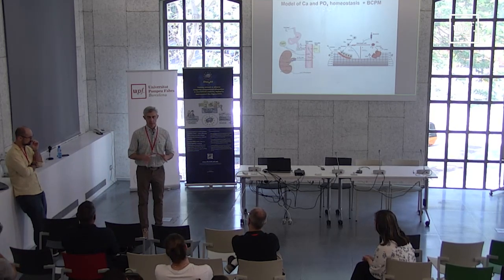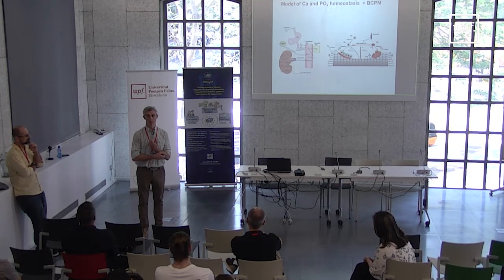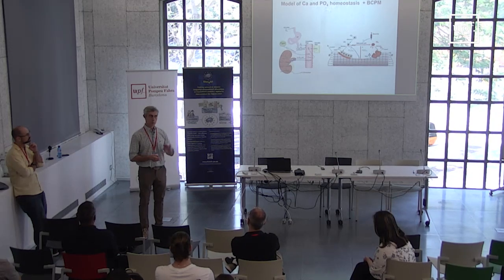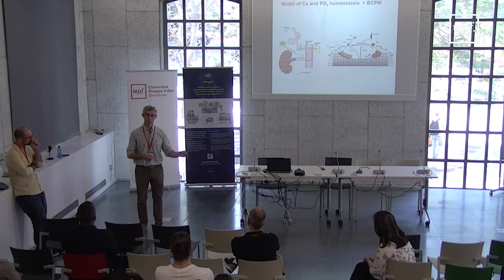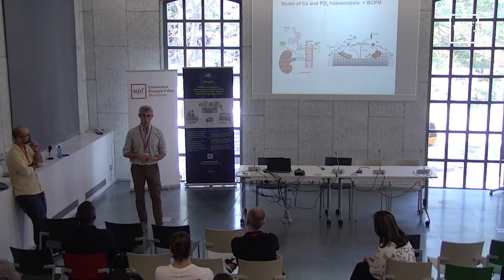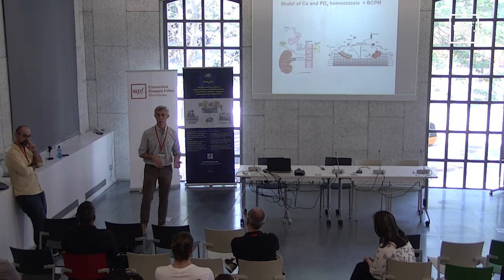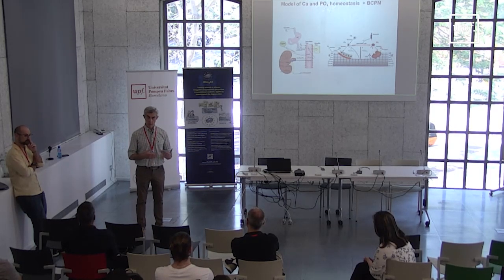Yep. This model I presented today is just a local model. So we could say that it's applied on an average bone, but actually we're modeling just one bone site of a given porosity. So we can use it for trabecular bone at a given bone site or cortical bone separately. But we are currently working on the inclusion of this model into a finite element model of a whole femur. And there we could investigate the interaction between cortical and trabecular bone.